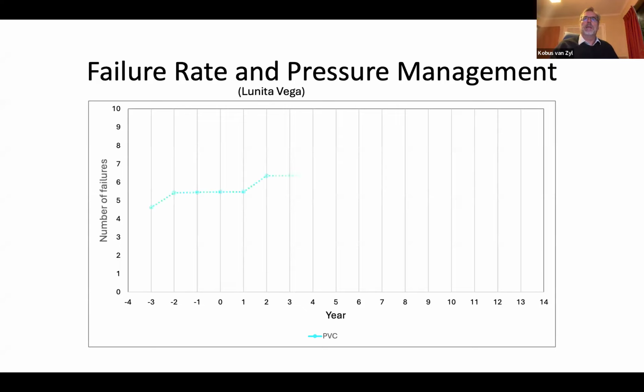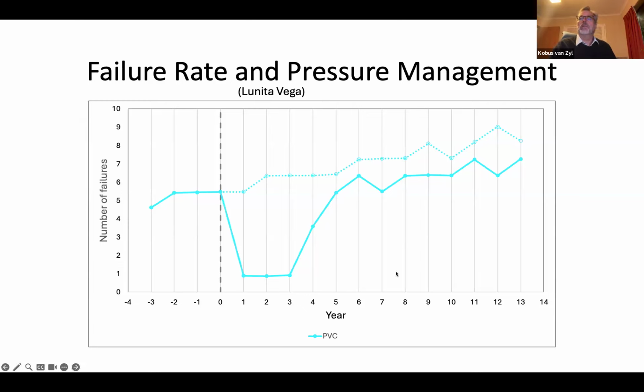This is what we found for PVC. In a typical DMA, the number of failures is increasing with time. But if we now implement pressure management in year 0, as I labeled it here, what we find in our model is that the burst rate will drop dramatically. It'll stay down for 3 years, and then it will start increasing and get much closer to this dotted line, which shows where the burst rate would have been if we kept the pressure at 70 meters. And the solid line shows what happens when we reduce the pressure to 55 meters. So you get an initial significant reduction in burst rate, but then there's a sort of correction where that effect is reduced.